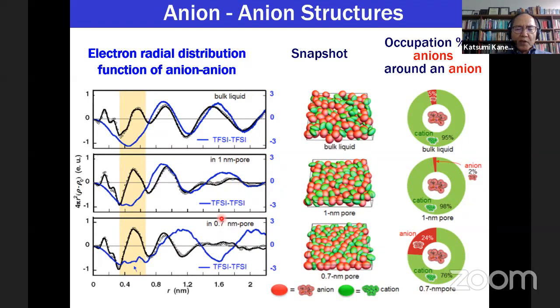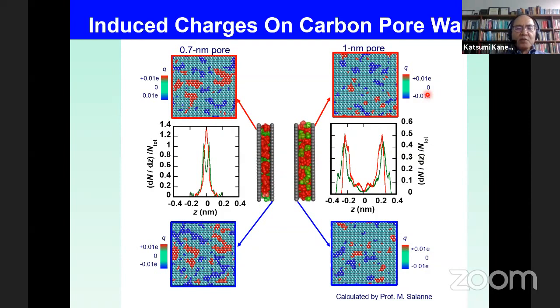But if we confine the EMIM TFSI in 0.7 nanometers, we can observe this negative peak shows just a little bit of upward shift. Then we counted the real number of anions occupying this first coordination shell around the anions. This is the result. Around the anions in the 0.7 nanometer case, nearly 25% of anions occupy the first nearest neighbor shell. But in the bulk case it is very tiny, nearly five percent, due to the collisions. So a very unique behavior is observed.